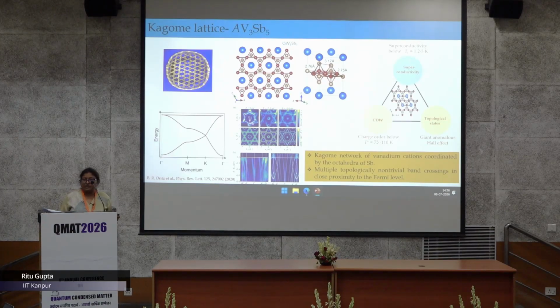Because of this very interesting geometrical structure, they have inherent frustration, and due to that they show several non-trivial features in their band structure, including Dirac-like crossings, Van Hove singularities, and flat bands around the Fermi level, which is indeed also observed in ARPES studies. Because so many non-trivial features are there around the Fermi level, many interesting physical phenomena happen in these compounds, including charge order between 75 to 110 Kelvin, followed by a superconducting transition between 1.2 to 3 Kelvin, and then topological features. Related to that, people have observed a giant anomalous Hall effect.